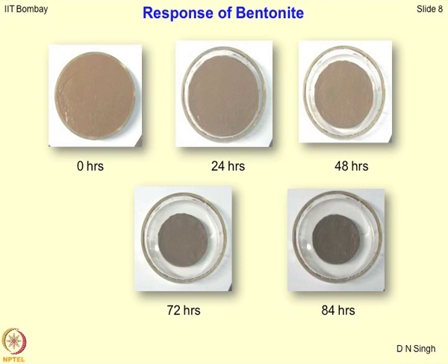in 0 hours. If you start from this state of the shrinkage limit test, after 24 hours, 48 hours, 72 hours, 84 hours. Yeah, so this is the most stable state of the material, which is arrived at after 84 hours. So it takes 84 hours of air drying to achieve the most equilibrated state.